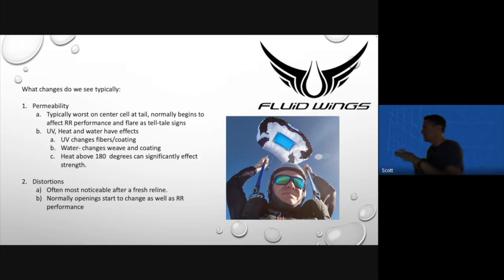It starts to lubricate these, and the orientation of that calendaring starts to go away. So that's one change with water that happens. It's not a physical property change; it's a weave change, and that happens to some degree on coated fabrics as well. So we see all these effects, and we start saying, "Oh my, I've got high porosity." So we all do a porosity test. Oh, it must be it. Must be what's causing it.